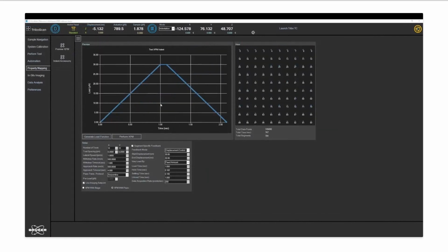Now, this is the area that I've scanned for an XPM test, which is accelerated property mapping. And I've created a load function. This is the displacement control test going down to 30 nanometers and a 10 by 10 grid with 200 nanometer spacing. So it lifts off the surface and reseeks to find the sample surface. Basically uses a trigger force to identify the surface.